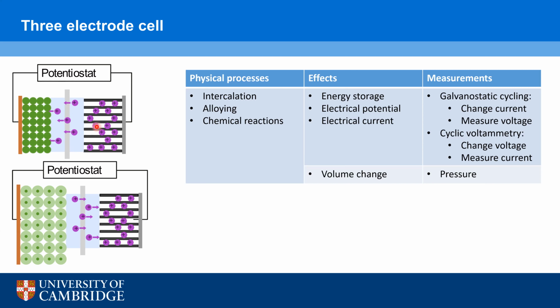When we develop a new battery material, we typically test the material in 2 different configurations. To begin with, we start with a half cell where we have the working electrode that we then test against a lithium metal electrode. The lithium metal electrode acts as both a counter and reference electrode, because we have an excess of lithium metal, meaning that when we electrochemically cycle the half cell, the potential of the lithium metal doesn't change during the cycling, meaning that it can act as a reference electrode. So by measuring the potential difference across the two electrodes, the working electrode and the lithium metal, we can track the chemical changes and reactions undergoing at the working electrode during the cycling.